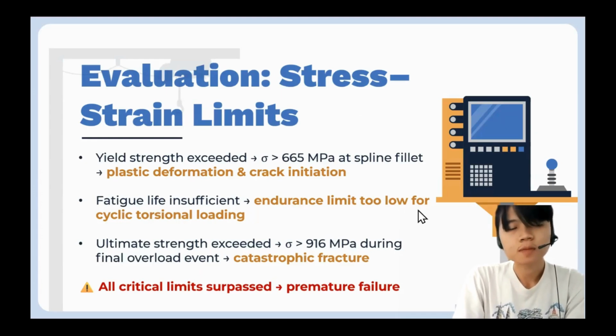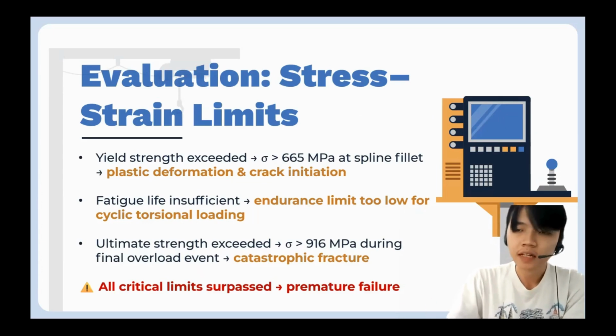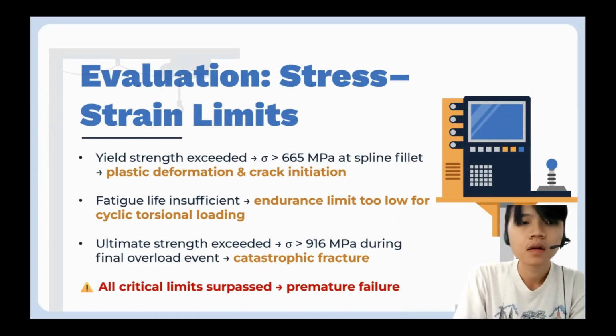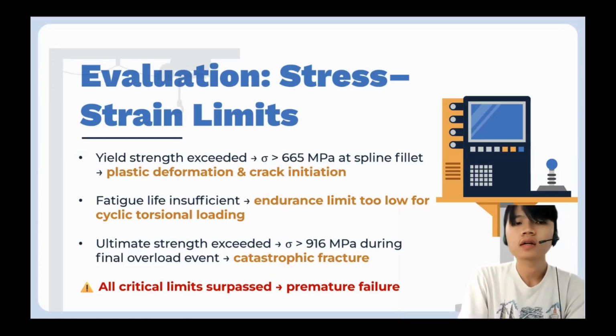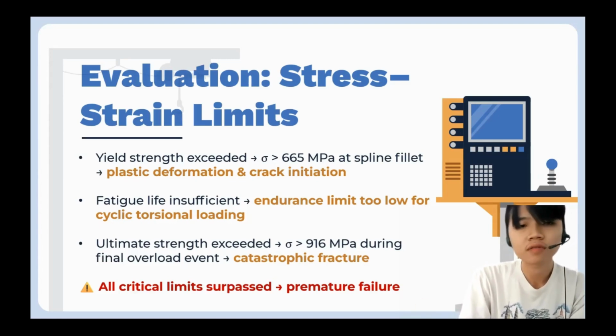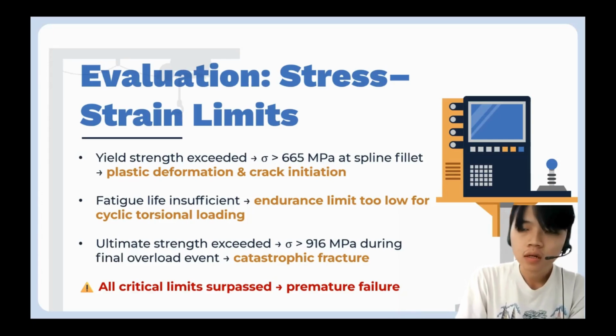When we evaluate the results against stress-strain limits, the evidence is clear. The effective stress at the spline root exceeded the yield strength of the actual material, and this triggered the plastic deformation and crack initiation. Over time, the endurance limit of the material was not sufficient to withstand the cyclic torsional loading, and this led to fatigue propagation. And finally, during a high torque moment, the applied stress surpassed the ultimate tensile strength, and this caused the catastrophic ductile fracture. So, in other words, every critical material limit, namely the yield, the fatigue, and the ultimate, was exceeded, and this explains the premature failure.